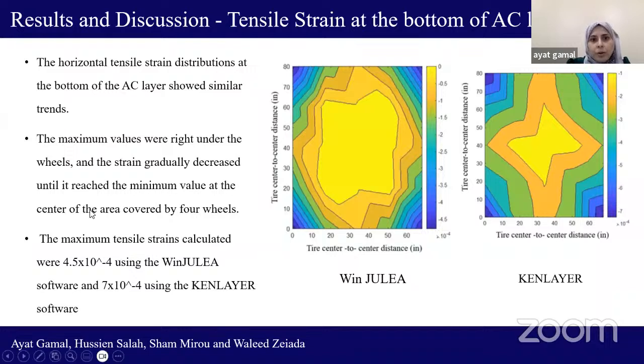Moving to the results section, we computed tensile strains at the bottom of the asphalt layer using both software. As we can see, the horizontal tensile strain distributed at the bottom of the AC layer showed similar trends, but actually different values. The maximum value is right under the wheel, and the strain gradually decreases until it reaches the middle between wheels. This is expected. The maximum tensile strains calculated were 4.5 times 10 to the power minus 4 for WinJULEA, and 7 times 10 to the power minus 4 using KenLayer.